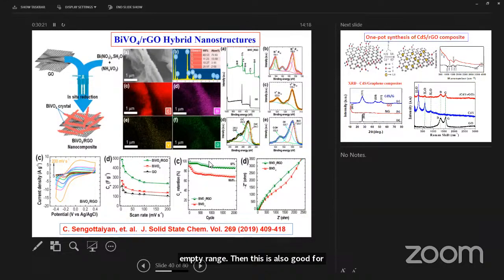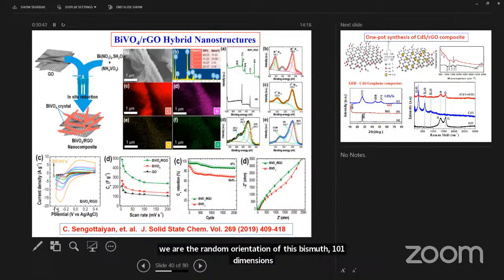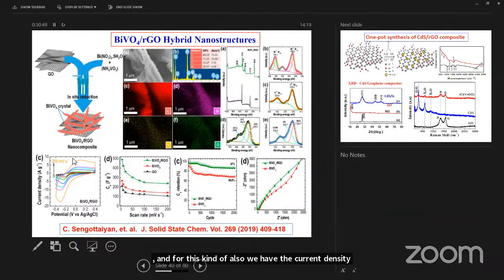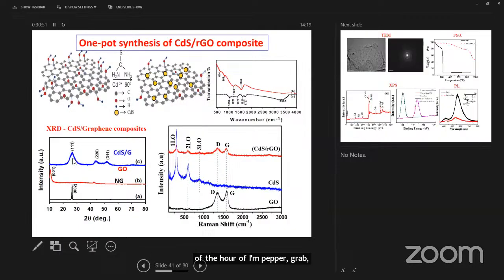Then these are different kinds of morphology: the bismuth vanadate in one-dimensional structure, which was integrated with RGO by in situ reduction process. Then you have the random orientation of these bismuth vanadate one-dimensional structures, and this is the Raman imaging. And for this kind of electrode also, we have the current density of the order of ampere per gram, which shows that these electrodes have very high power density.